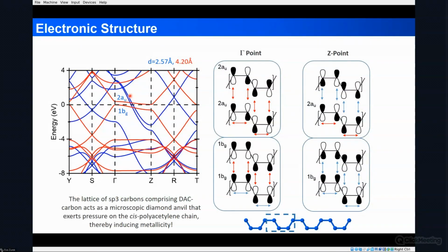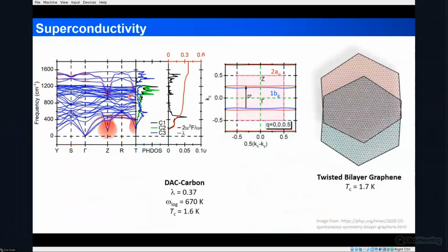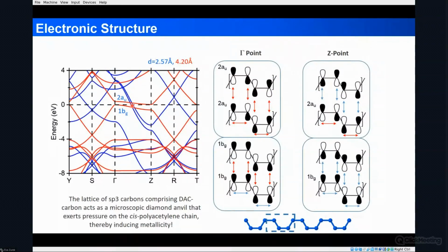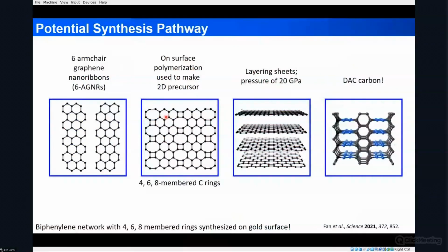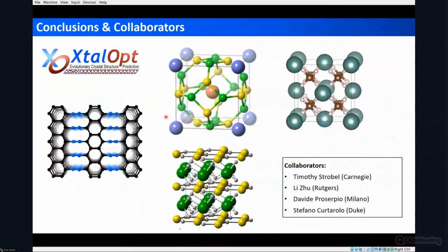And if you have this metallic carbon type system, you could potentially have superconductivity. And we studied that. The superconducting critical temperature of this so-called DAC carbon is quite low. It's only 1.6 Kelvin, but it's quite similar to that of twisted bilayer graphene, which is one of the rages in materials science nowadays. And we can show that the superconductivity is due to these two flat bands. Okay, and we predicted the synthesis route. So that's all I wanted to say.